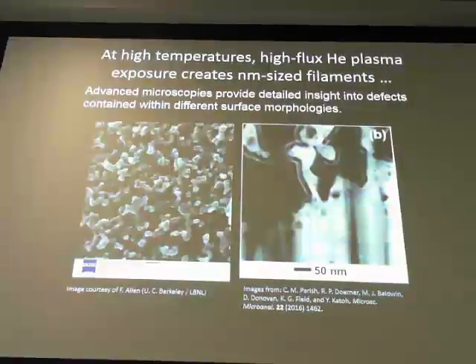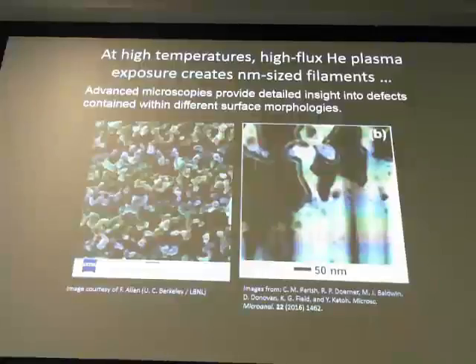Well, they've actually observed this in a practical tokamak, in Alcator C-Mod. Alcator has moly tiles on the interior, but they put a tungsten row in there, and they ran with the mixed species plasma, and they saw this there. So it's not strictly an artifact of angle of incidence. I appreciate your point that it has been observed in a practical tokamak environment. Well, I know that Doerner and friends have also tilted the sample and tried to get multiple exposure angles on it. Yeah, right. But I appreciate the point. It is something that has been observed in a practical environment.